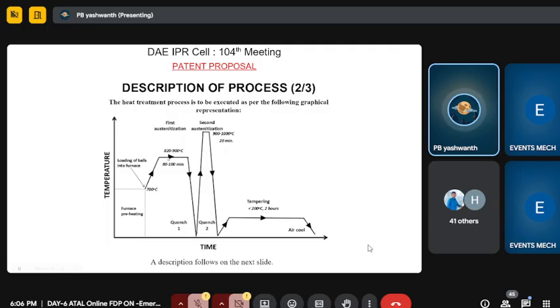which is 820 degrees Celsius. It was soaked for 100 minutes. Then again it was quenched, first quenching. Then again it was raised beyond this temperature, which was first 900, second 1000 degrees Celsius. We call it first austenitization and second austenitization.